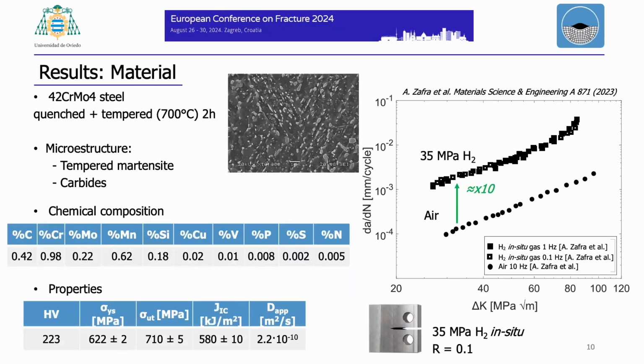So results. We use a 42CrMo4 steel, quenched and tempered at 700 degrees for 2 hours. The microstructure is a tempered martensite with carbides. Here you have the chemical composition and some properties: the hardness, the yield strength, ultimate strength, the fracture toughness, and the diffusion coefficient. As I told before, this steel was already evaluated, but under in situ gas conditions. And in that study, we observed that in hydrogen ambient, the crack growth rate increased, it's like 10 times faster. These tests were performed with CT specimens.